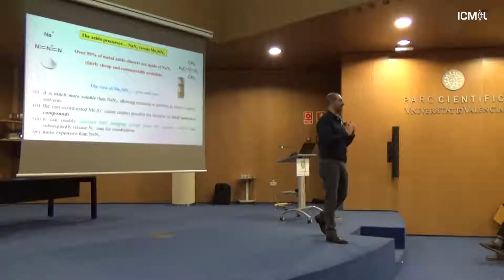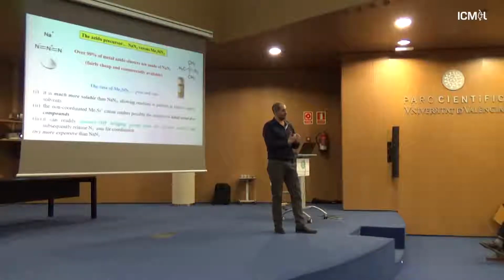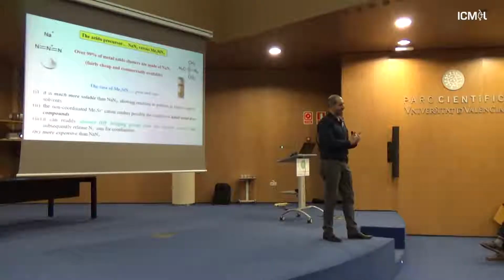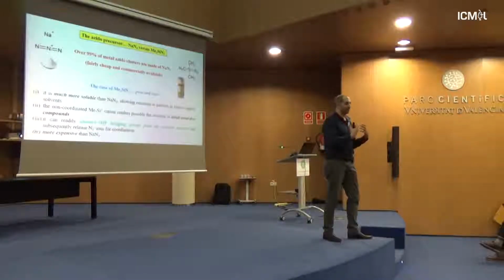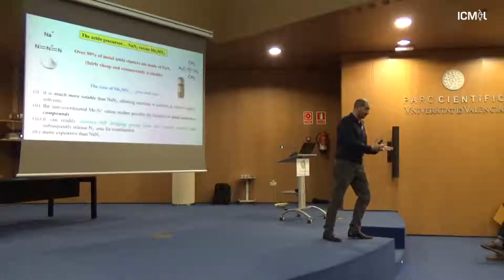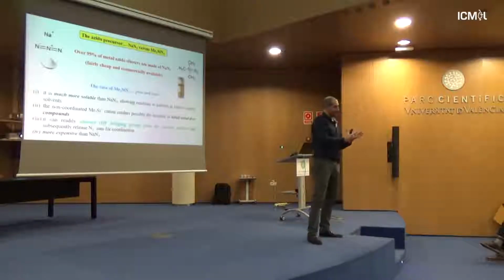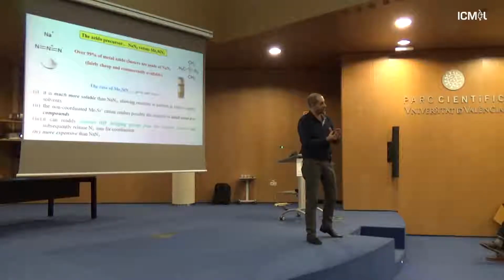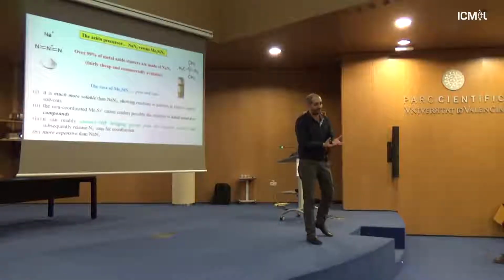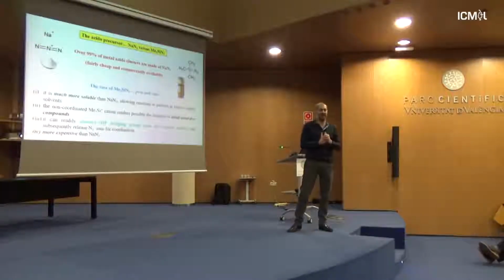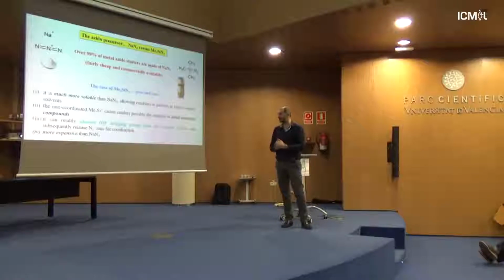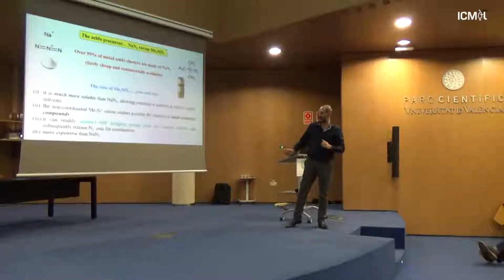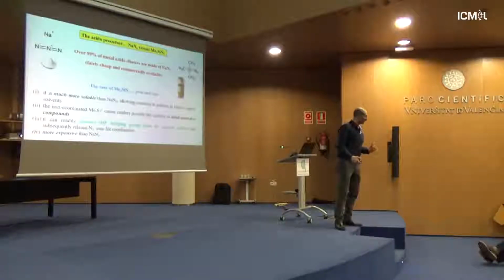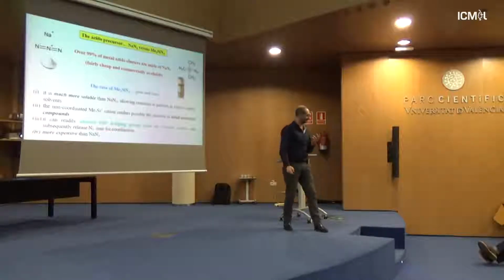But this is not easy at all, because you cannot underestimate the usefulness and necessity of the organic chelate ligand. What's that? The thermodynamic stability. Those organic ligands provide thermodynamic stability to the systems, which makes you eventually able to crystallize those compounds. Because we are all, at the end, judged by our ability to grow crystals. That's the only way to determine the crystal structure. Good. Of course, this is something that we, as supervisors, only worry about. Trimethylsilyl azide is at least 10 times more expensive than sodium azide.